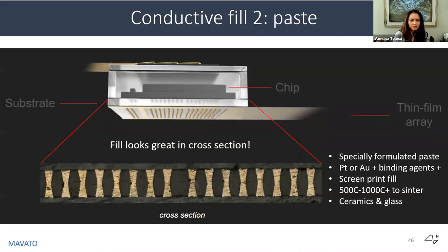So you try a more conventional method, a screen printing process. Here's a cross section of an actual substrate where conductive paste fill was used. In this process, the fill is done by screen printing. So you have this paste that you essentially squeegee into the holes until it fills up, into these via holes that you had created earlier. This has to be done iteratively.